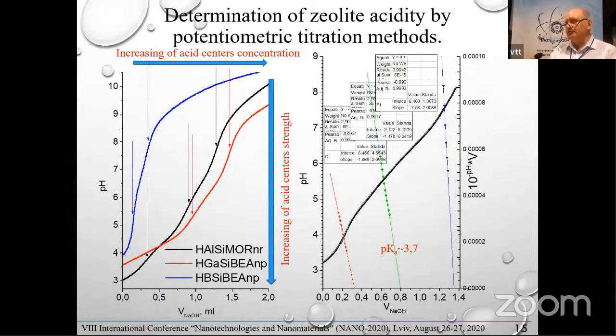We try to make some correlation between acidity, especially acid center strengths, and catalytic activity, especially selectivity in this process. For the precise determination of acidity, especially acid strengths, we use a method of potentiometric titration, with the possibility of exact determination of the acid centers present in zeolites.